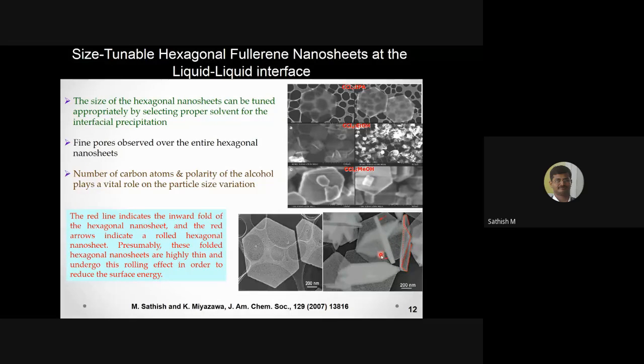So what we observed is there is a high surface energy, since these nanosheets are stored in a solution. When you dry it over the TEM grid, what will happen is the solvent evaporates, so the surface energy also increases. So in order to avoid the high surface energy, these sheets undergo rolling, so that the exposed surface of the sheets may be reduced. That is generally possible and occurs in all sheet-like structures, unless you have some surfactant molecule to stabilize them. These surfaces are very reactive, and they want to reduce this active surface area, so they roll up. Because of this, we could see some kind of rolled sheets. Okay.